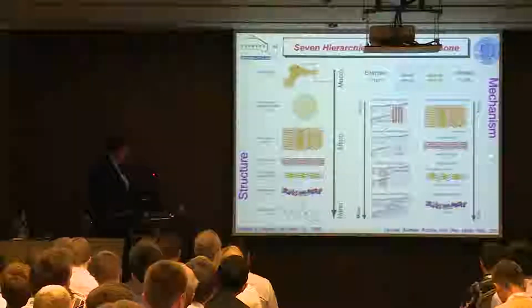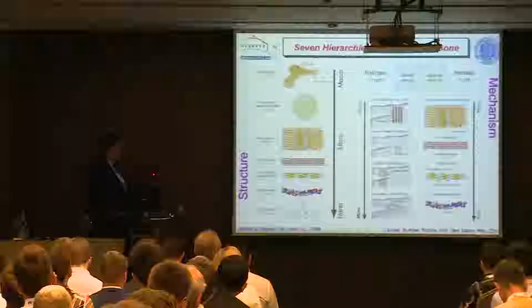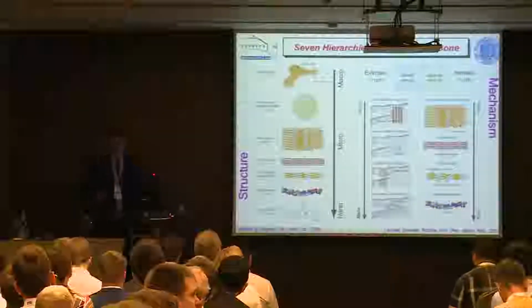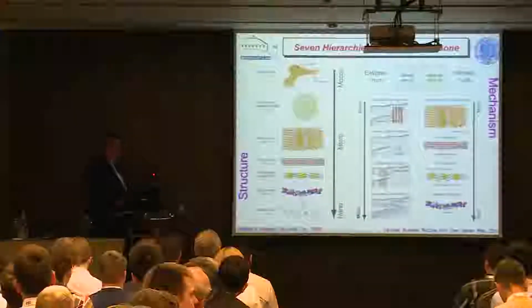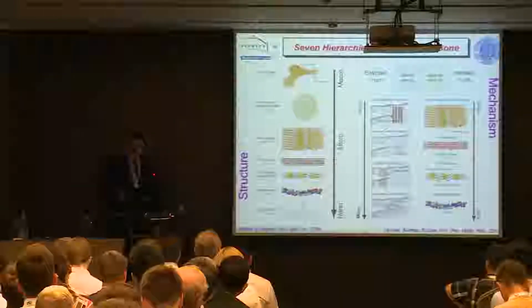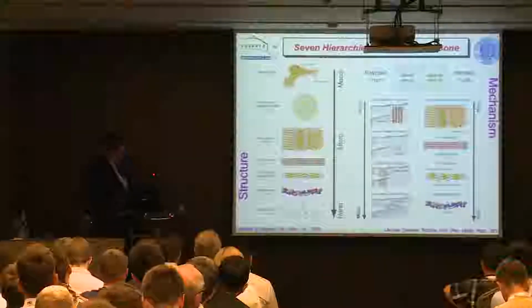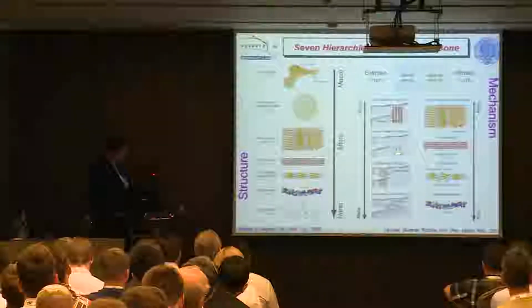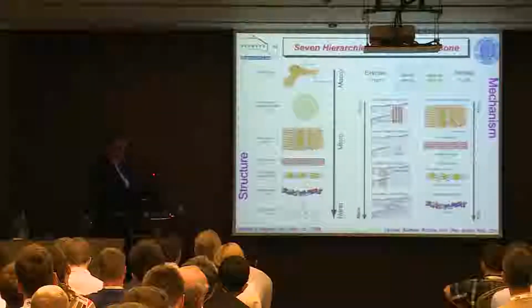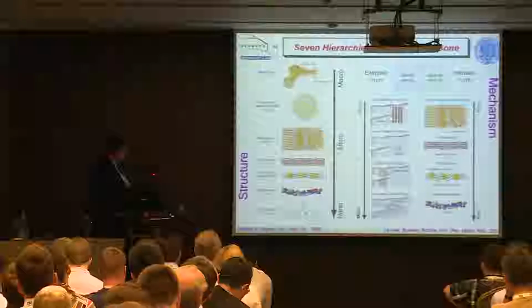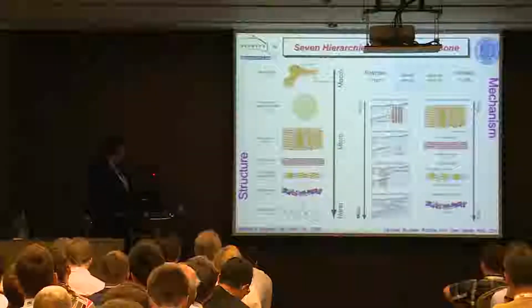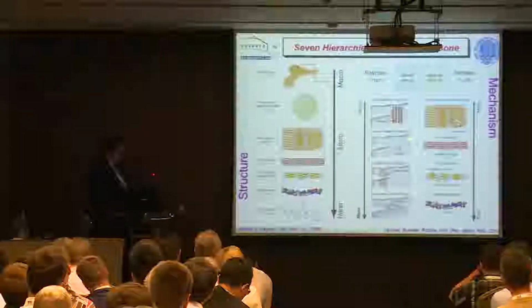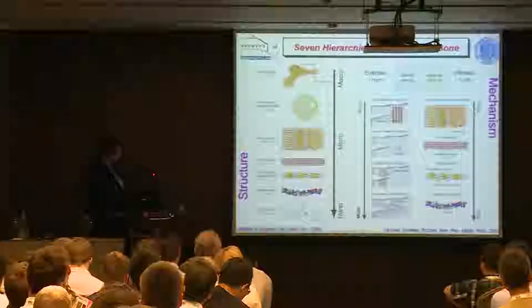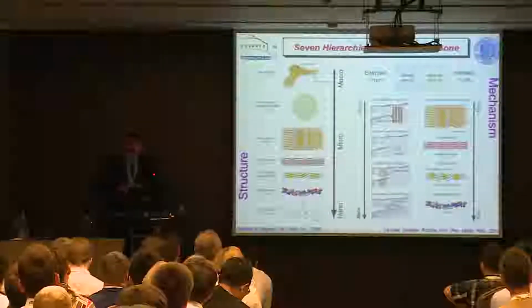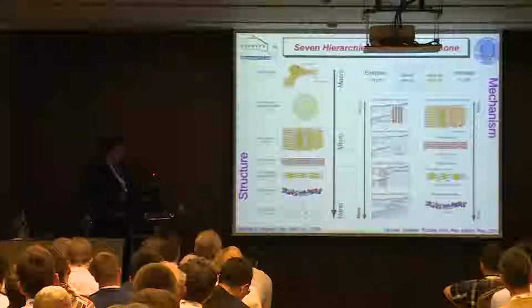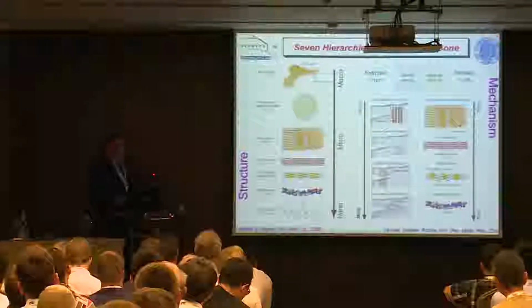So the toughening mechanisms in bone at these sort of scales are plasticity, and the plasticity is predominantly this fibrillar sliding. But then if you move up in scale to way above a micron, and you look behind the crack tip, you see mechanisms that you'd see quite readily in a ceramic. There's a lot of microcracking in bone. It's very important. It leads to remodeling of bone. It's also an inelastic mechanism, if you like, of sort of pseudoplasticity. But cracks then grow into this sea of microcracks, and little regions in between those microcracks are bridges, and then you get very strong deflection. These columns here are the so-called osteons. These run along the axis of the bone. These are Haversian canals inside. The boundaries of these osteons, this is how bone remodels, tend to have a higher mineral content, and cracks will tend to deflect along those boundaries.